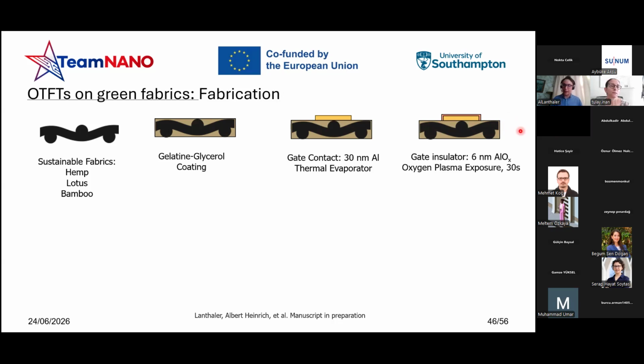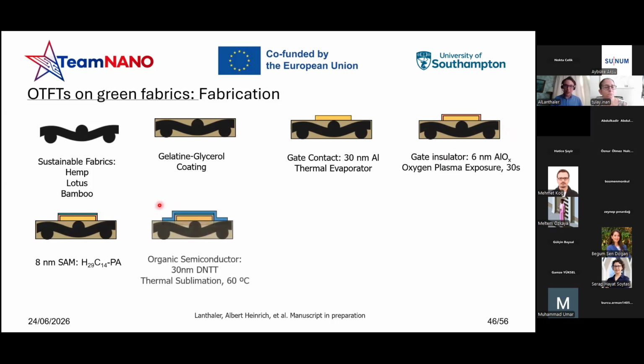The first one is, through oxygen plasma exposure, we were able to grow 6 nanometers of aluminum oxide for 30 seconds. And then the second part is 8 nanometers of self-assembled monolayer. In this case, it's an octadecylphosphonic acid coating attached only to the aluminum oxide layer. Then, for the organic semiconductor, through thermal sublimation at 60 degrees Celsius, we were able to deposit 30 nanometers